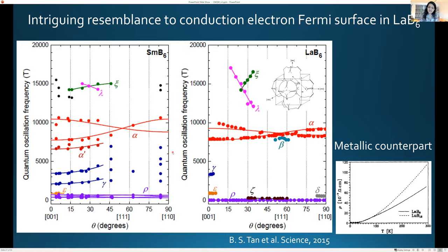The other thing to point out is that I can't actually back calculate and get a geometry from just the frequency, because that would be over-parameterized basically. So what I'm trying to do here is actually look at examples. Ordinarily for a metal, one would have a band structure. One could calculate the Fermi surface and compare the calculated Fermi surface with the observation of frequency, which I can't do here, because if one were to calculate a band structure, it would be zero. You would see nothing here, no frequencies.